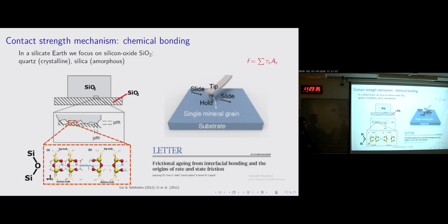Silicon oxide is silicon with 2 oxygens, and its crystalline form we call quartz, and its amorphous form, like glass, we call silica. And we take these 2 blocks again, they're both made of silicon oxide, and studies have shown that when a small scale contact between these 2 solids occurs, then silicon-oxygen-silicon covalent bridges form across the interface. That's chemical bonds right there. And atomic force microscopy studies, done with the same slide tests that we looked at before, concluded that frictional aging comes from the chemical bonding and not just the contact area. These silicon-oxygen-silicon bonds are really, really important, and that's what controls the frictional response. And that is completely missing from all the models that are typically used in earth science to model earthquakes and also landslides.